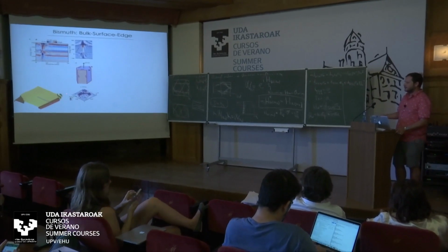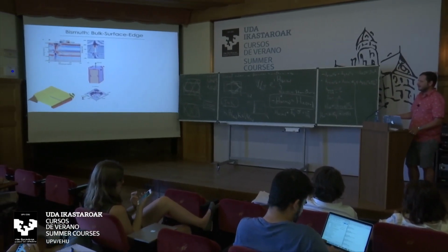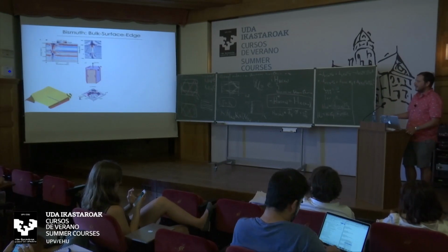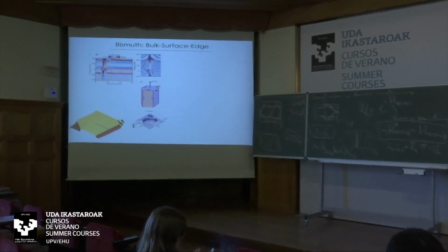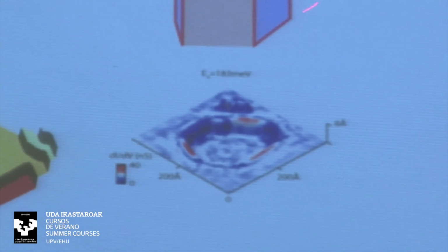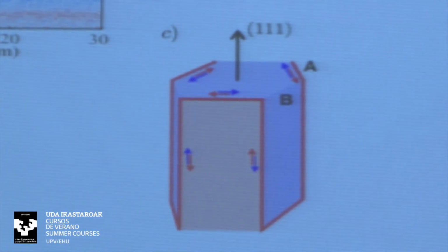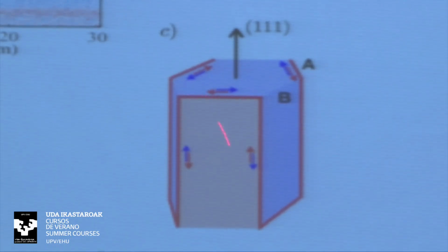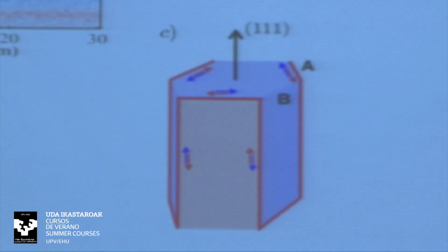So this is a differential conductance image, the density of states in real space at the edges of these step edges, and you can see that on one we see some increased density of states, on the other we don't, and it's alternating along the edges. And this is a calculation by Andre and Titus of what they would expect from the symmetries of bismuth, mainly the inversion symmetry, which appears in bismuth, together with the C3 symmetry, which is less important as far as I understand.